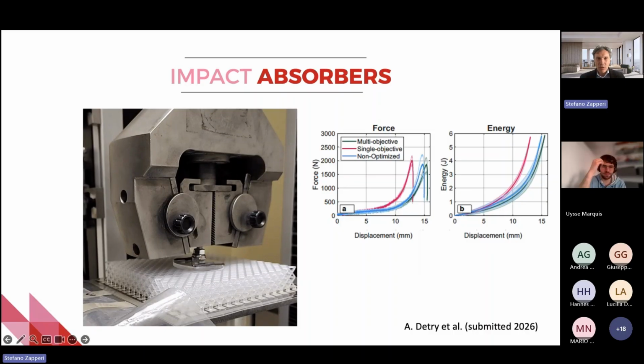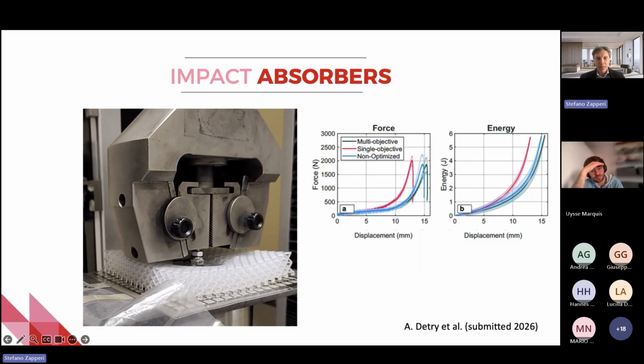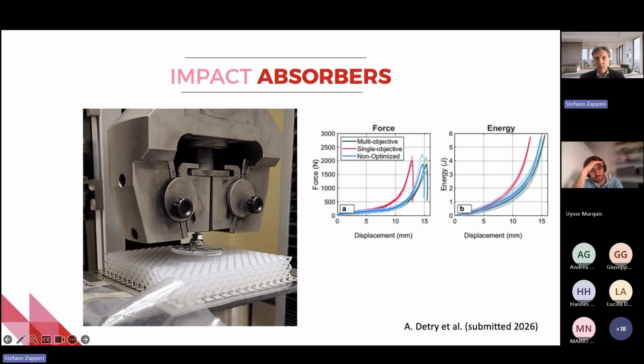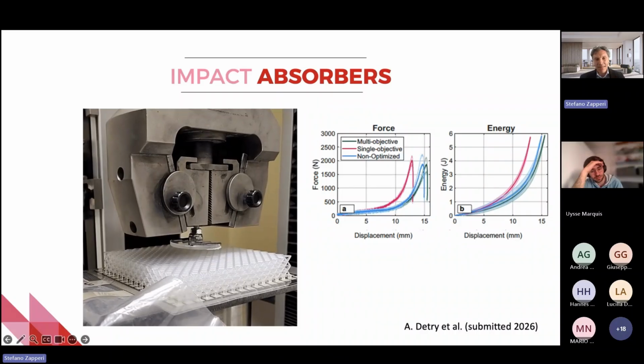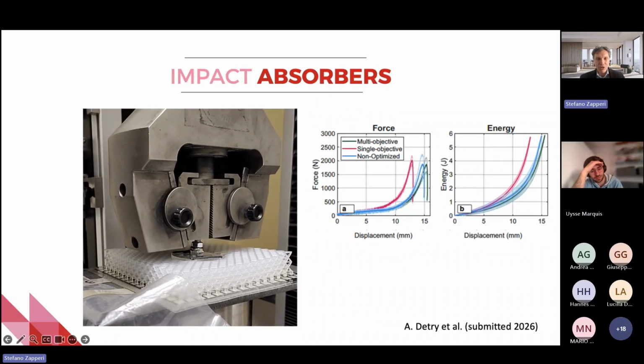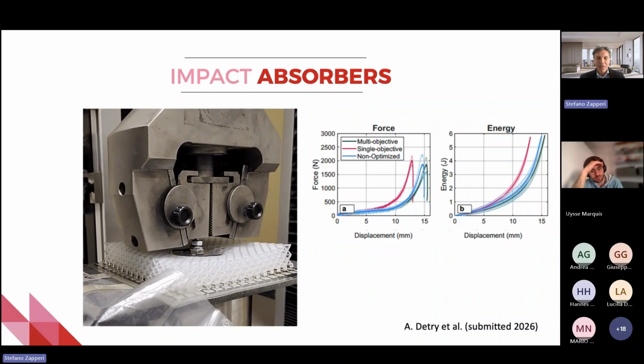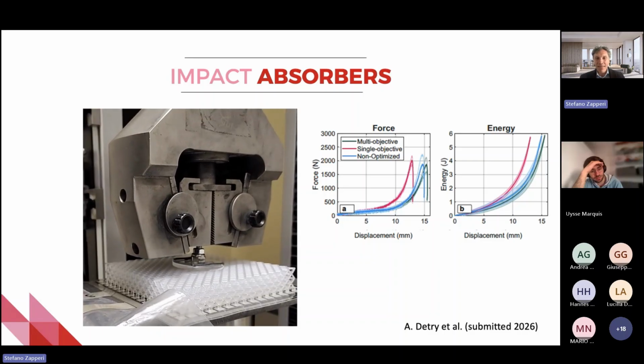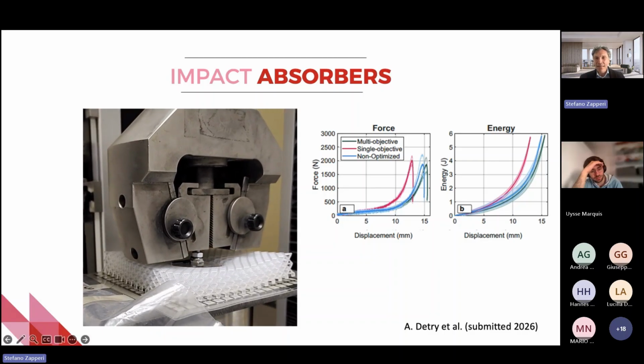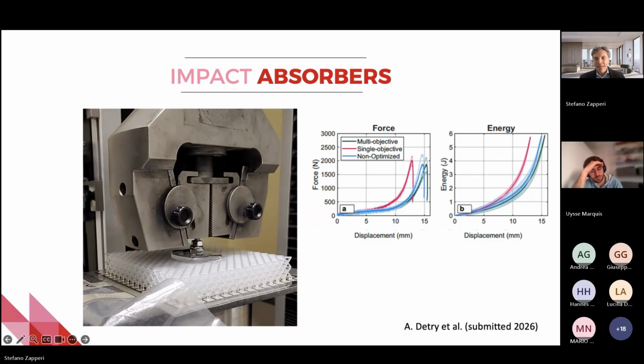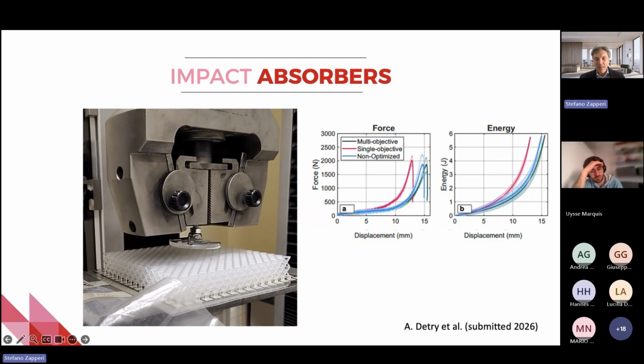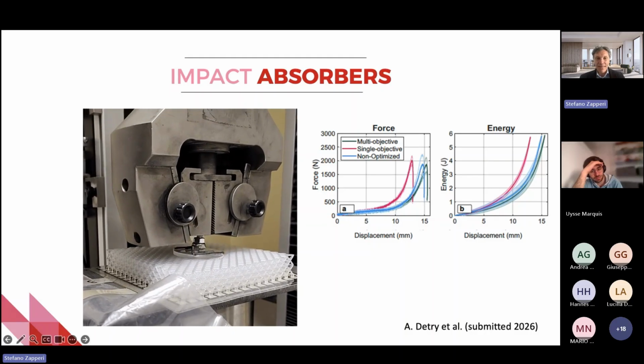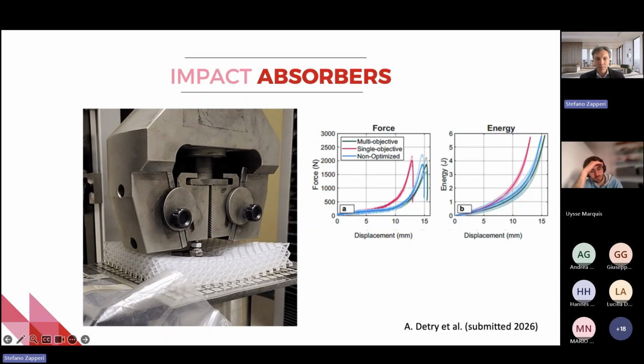And then we tested whether this is also good for impact absorption, and indeed it does. So if you do an impact test, this is not an impact test, this is a quasi-static test, but I just show you because I have a nice movie. But we did also proper impact tests, and indeed there is better energy absorption for this optimized structure with respect to the original one.